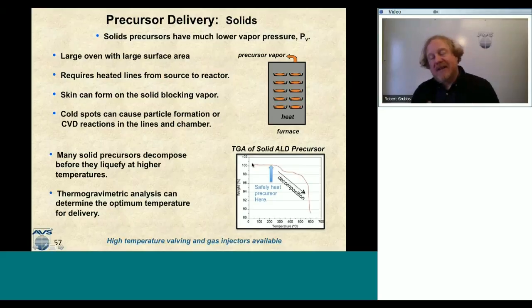So here's an example of a TGA on the lower right-hand side of your screen. I put a solid into it, and as I start to see the weight loss with the TGA, I see that it decomposes if I heat it to a high enough temperature. And so I don't want to work in that temperature regime with my chemical precursor. I want to be somewhere before this first cliff right here. I want to run my furnace or heat my chemical precursor somewhere there so I can have a safe delivery of the precursor, but not necessarily decompose it inside the lines of my reactor.